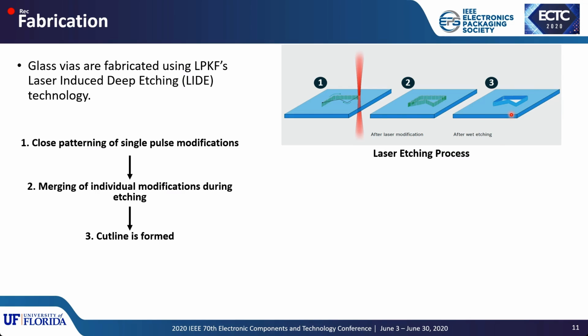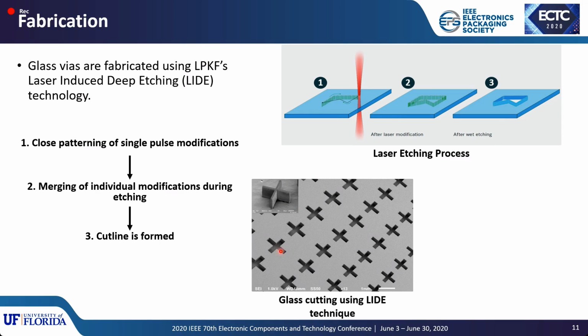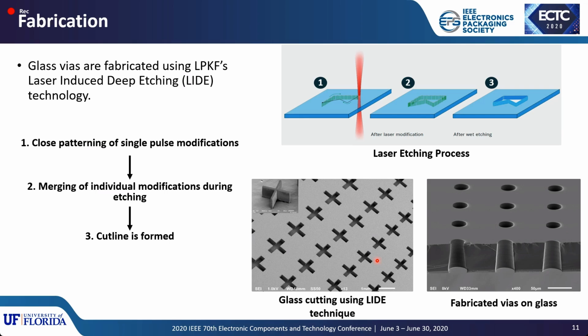So using this technology, different features can be easily fabricated on glass, as you can see here, of different shapes. Another important thing to notice is, as you can see from the SEM images, the glass is free from any cracks and any defects. Also, at the end of this process, the properties of the glass remain the same, as the internal stress formed inside the glass during this process is very low.